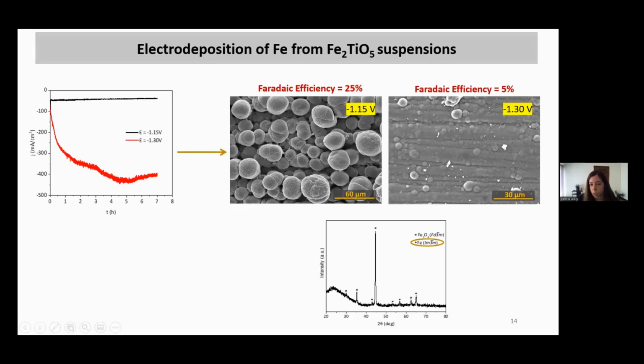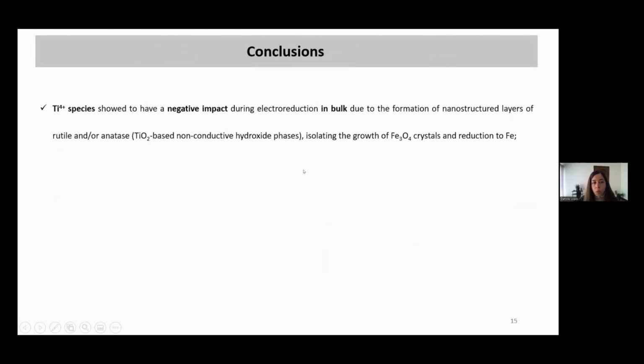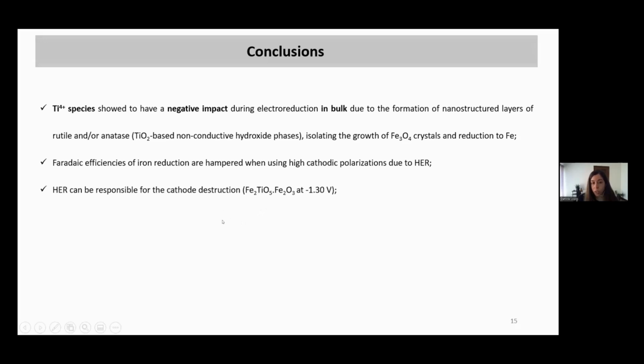Here you can see the difference between the deposits. We have a drop of efficiency from 25 to 5% when we increase the cathodic polarization, again because of hydrogen. So in terms of conclusions, we can say that titanium species really do have a negative impact in the bulk electroreduction because we can observe non-conductive phases forming, like rutile and anatase. They isolate the growth of the crystals and totally block the reduction. We have really low Faraday efficiencies because we needed to use high cathodic polarizations and hydrogen evolution was affected. Hydrogen evolution can also destroy the cathodes, like the example of the composite.